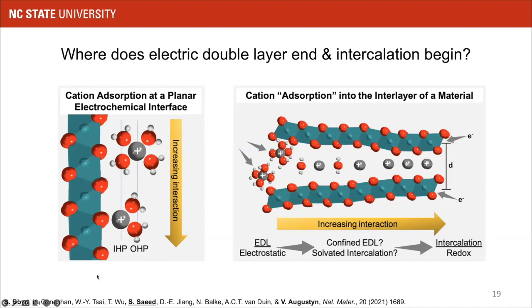And so for the most part, when we think about the electric double layer, we're thinking about planar electrochemical interfaces. So when we think about processes like cation adsorption, we think about this distinction between the adsorption of a fully solvated cation that would have a non-specific interaction with the surface. So in the cyclic voltammogram, for example, you would see no specific potential dependence. And then you also have specific cation adsorption where there's a chemical bond being formed between the cation and the electrode surface, including either full or partial desolvation of the cation, and that would have an associated potential dependence with it. And the distinction between these two processes, fully solvated non-specific cation adsorption and specific cation adsorption, is essentially how we describe double layer non-Faradaic capacitance and pseudocapacitance.